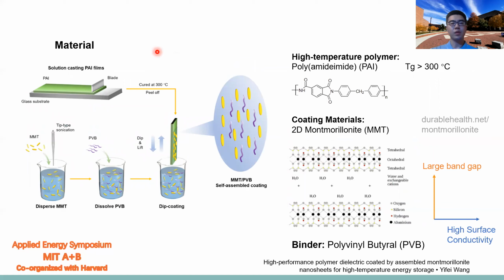And here we present a new method to improve the energy storage performance of polymer dielectrics. We utilized a 2D material, 2D MMT, to coat the surface of polyamide-imide. Polyamide-imide is a high temperature polymer, which has a glass transition temperature higher than 300 degrees C. From the structure, we find that this 2D MMT has a layered structure, and it has a unique property, which is anisotropy.